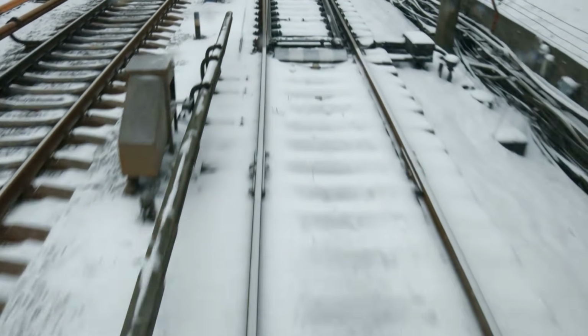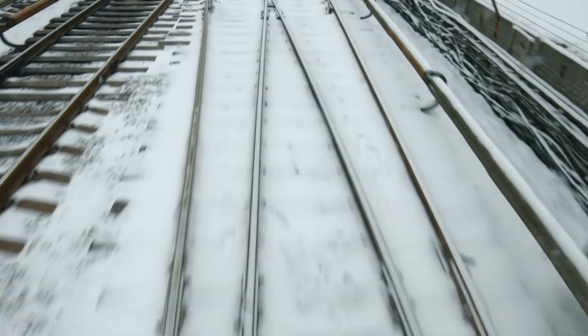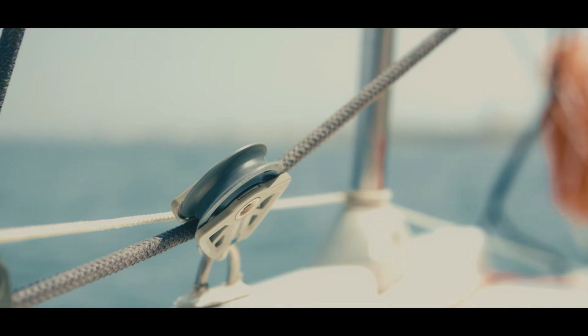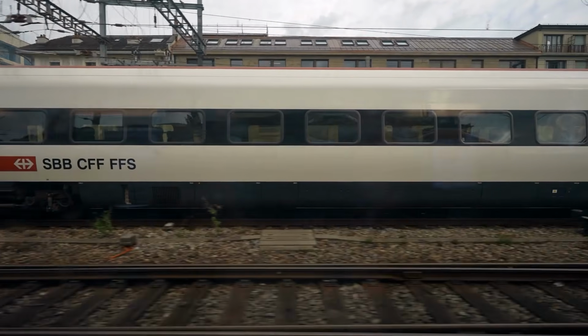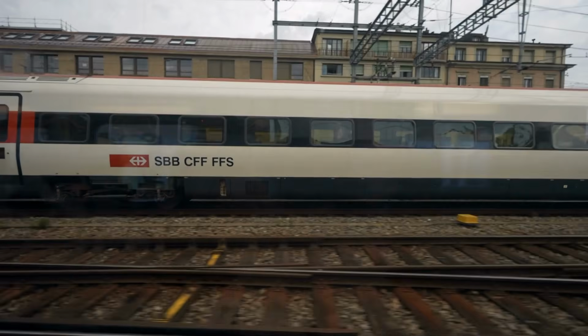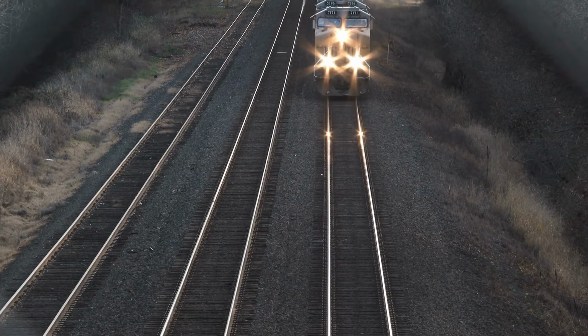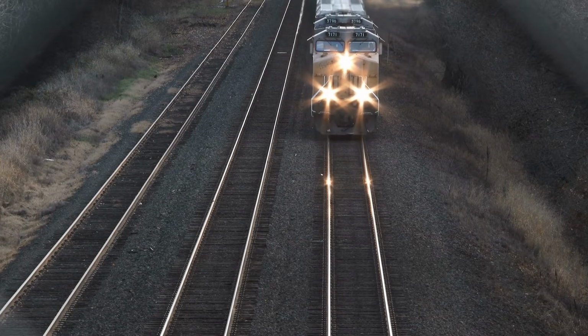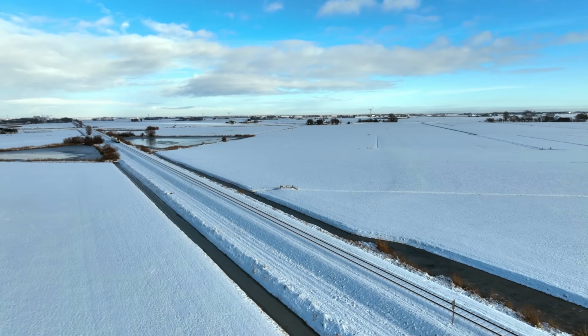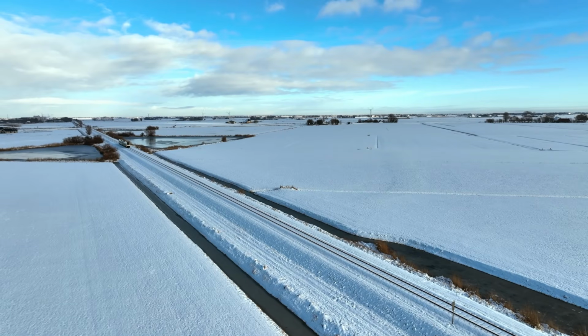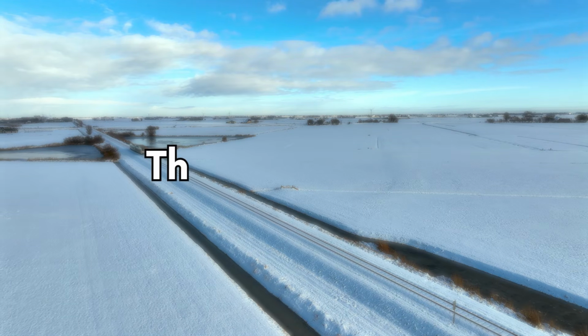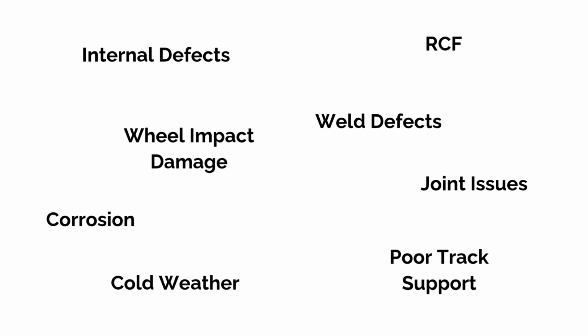In jointed track, rails can only contract so far before the joints get to their limit. When cold weather comes, the rails want to contract, but they can only contract so far. This puts them in a state of high tension, with a high level of tensile forces. If the rail already contains a crack, internal defect, a weld weakness, or corrosion damage, that sudden increase in tensile stress can make final fracture more likely. This is why it's typical to see a spate of broken rails during or just after the first cold snap of the year.